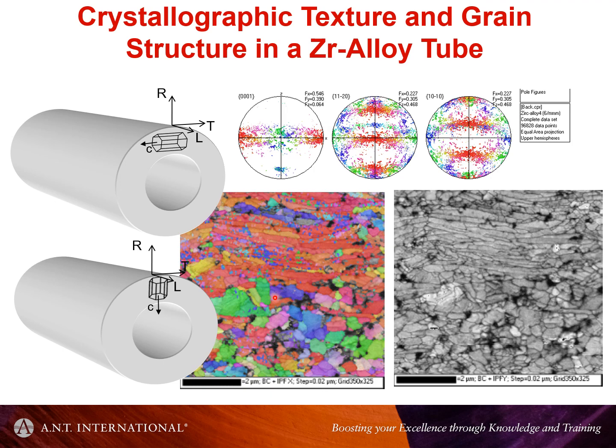So we have a cold work grain which has this orientation, and when it recrystallizes, it rotates about the c-axis and gives you this rotation difference, but the c-axis is still more or less up in the radial direction.